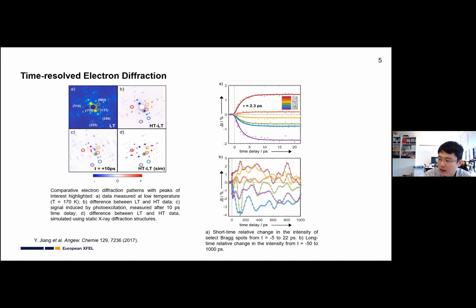Here we can see the short time relative change in the intensity of selected Bragg spots in the first 20 picoseconds, and the later one is for the first 1000 picoseconds. We can see there's only one step, with a time constant around 2.3 picoseconds, and we reached the high spin structure already. For the long-term one, we start to see a lot of phonon oscillation, but this is not really related to spin crossover dynamics.